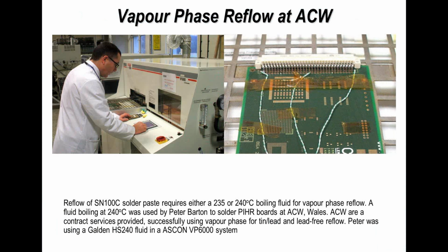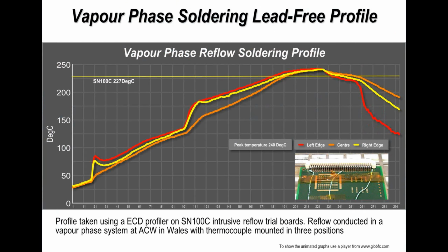And you can see how I'm monitoring at the edge of the connector and right in the center of the connector, because I know from experience that these are the hottest and coldest parts. But with vapor phase, I was actually able to reflow successfully at 240. With SN100C or any tin copper solder paste, it's got a reflow temperature of 227, so to use a 230 boiling point product would not really be acceptable. So 240 is perfect, and again it allows me to assemble the board successfully.